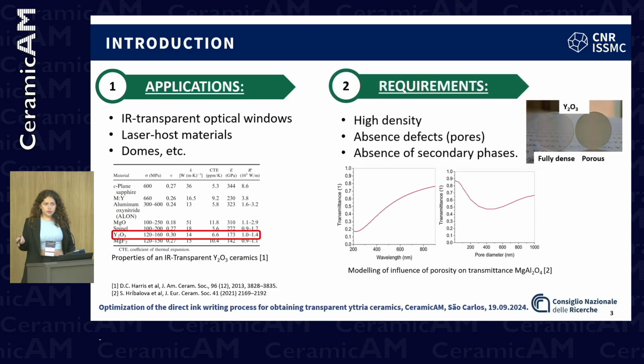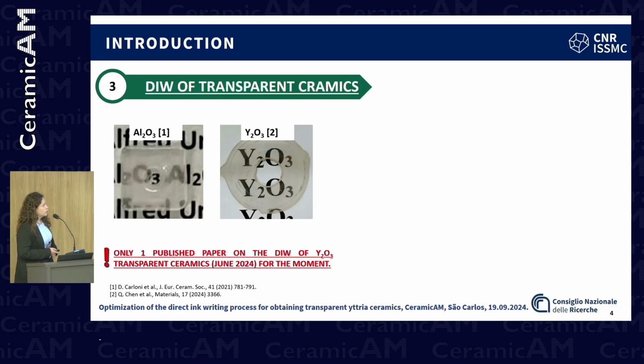To ensure these properties, there are some requirements, like high density of samples and absence of defects such as porosity or secondary phases. It's very important for such materials, since these defects are centers of light scattering, which leads to deterioration of optical properties, so we should avoid them in any case in our samples.